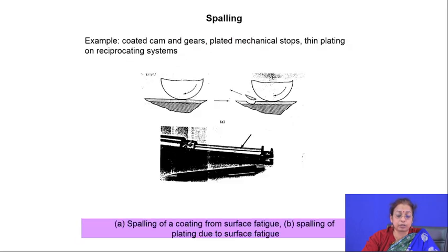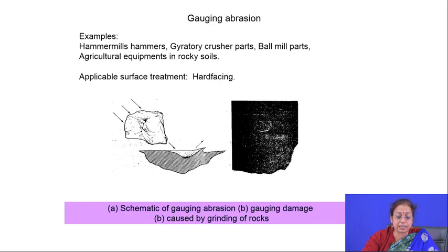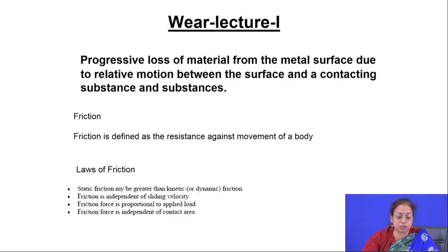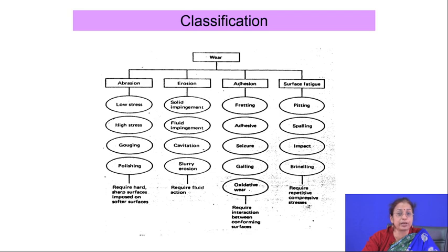When you talk about typical polishing wear, the surface looks polished in nature. When you talk about gouging wear, again on the surface there are big holes. Along with that there are also scratch marks. So, these features are very important to note down, otherwise it would be very difficult for you to recommend the typical surface treatment technique which you are applying for combating that kind of wear.